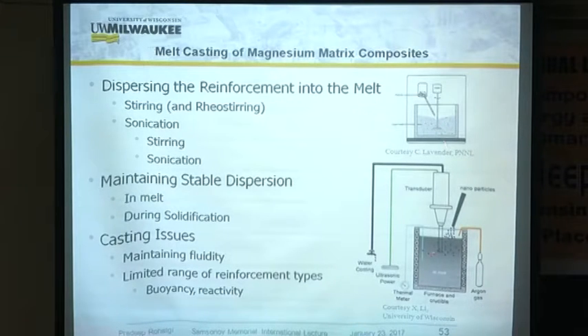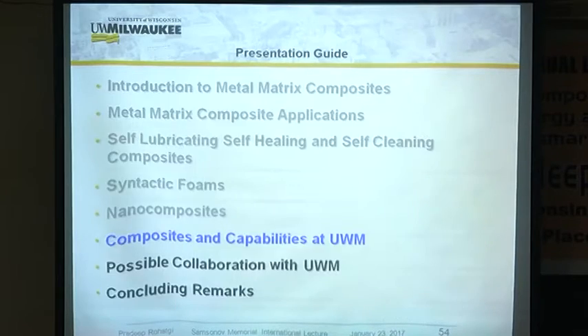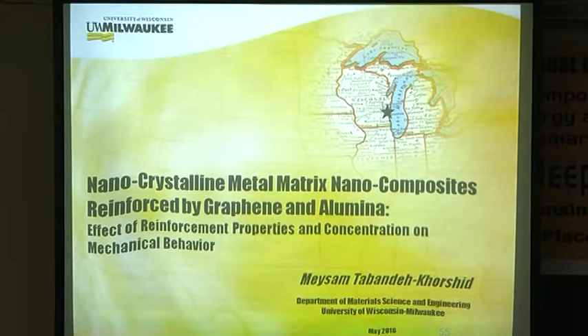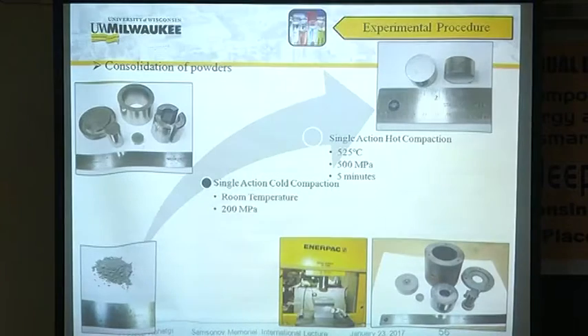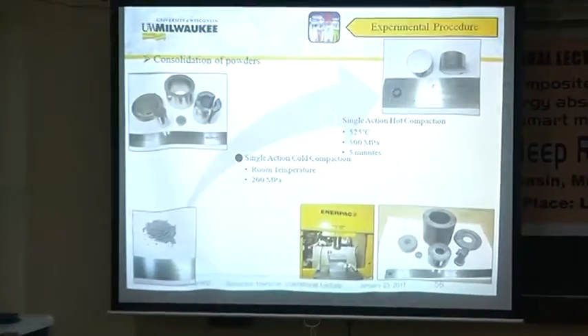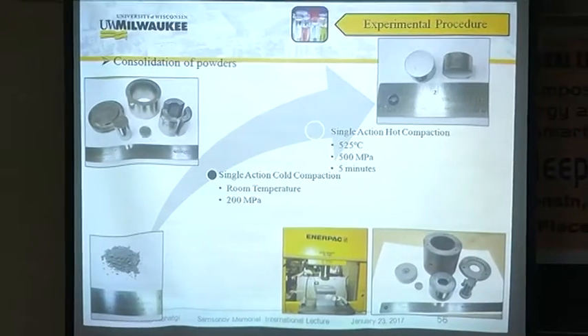You melt it, you introduce nanoparticles, you have a little ultrasonic dispersion and you just cast. Any simple foundry, many of them in Kanpur city itself, could be producing these things. My recent work is on putting graphene nanoparticles in aluminum. We are trying both melt, but powder metallurgy is the easier route because of the reaction between graphene and aluminum. So what we do is we ball mill graphene with aluminum, and then we cold compact, hot compact.